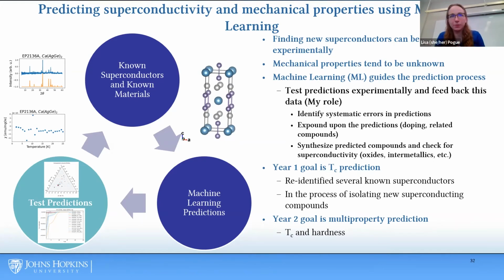So back on the superconducting work with machine learning, it's difficult to find new superconductors experimentally. And for many of these superconductors, the mechanical properties are unknown. And for QIS applications, you need to know both of these if you want to use them in devices. And so I've been working with these researchers to create algorithms to predict superconductors. And then I've been testing those predictions and also going through their lists and identifying systematic errors and materials that will not superconduct, but are identified as potential superconductors. I am synthesizing many of these predicted compounds and checking to see if they do superconduct. This past year was year one, and the goal was TC prediction.